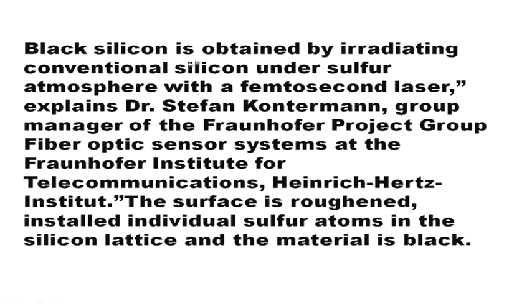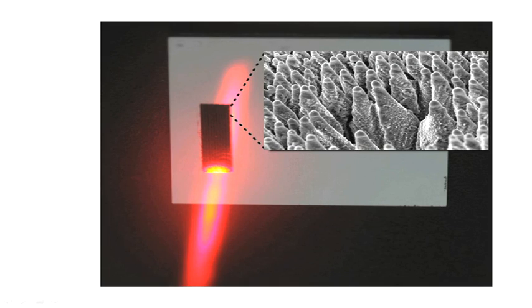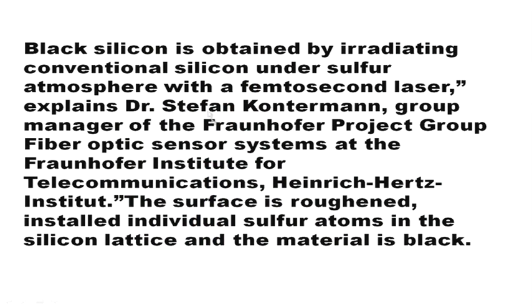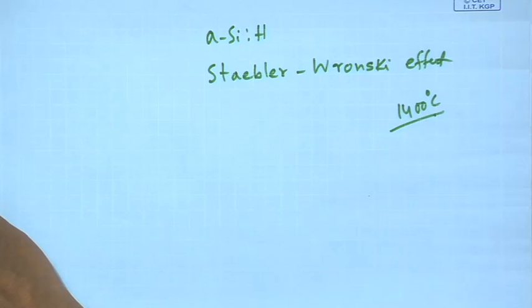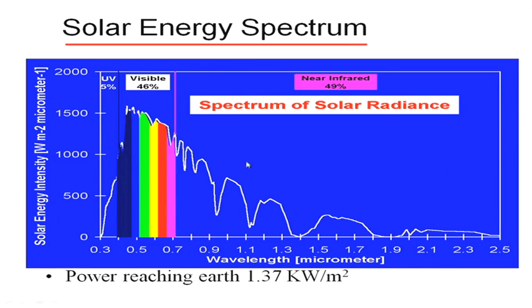Now, how is it obtained? It is obtained by irradiating conventional silicon under sulfur atmosphere with a femtosecond laser. And you see that the surface is roughened, individual sulfur atoms are installed in the silicon lattice, and the material becomes black. So, that is the black silicon. This region is magnified here. So, it is the sulfurization basically, of the silicon under sulfur atmosphere with a femtosecond laser. The advantage is that it can absorb infrared, as I have shown you on the first few slides. Some 25% infrared it can absorb. So, that means the efficiency can be increased apart from the absorption of the visible region.